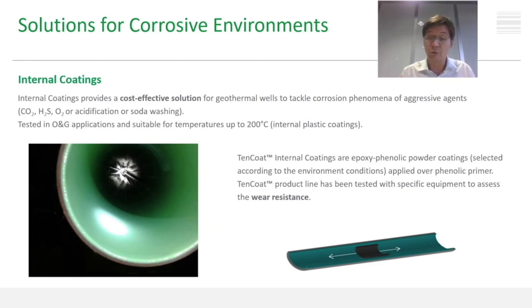As an alternative to the selection of sweet corrosion resistant steel or to sour corrosion resistant steel, internal coatings may be a cost-effective and interesting solution. Internal coatings are normally used in geothermal wells, considering the fact that they have the capability to resist both aggressive agents such as CO2, H2S or oxygen, and some specific operations that often need to be performed in the geothermal well in order to optimize productivity. This operation may be acidification or eventually soda washing. It's interesting to highlight that internal coatings, in particular epoxy phenolic powder coatings, are extensively used in the oil and gas business, in particular in mature fields.